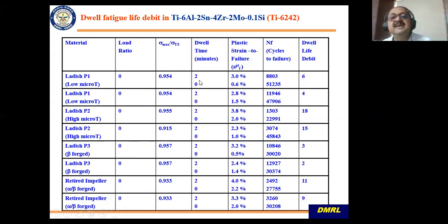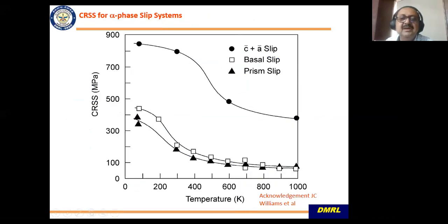And the dwell time was 2 minutes, and it was tested at 95% of the maximum. Maximum stress was 95% of the yield stress. And you can see in the low microtexture material, the dwell fatigue debit is much lower as compared to that in higher microtextured material. And then for beta forged, it is lower for various other reasons. I'll just show you the reason.